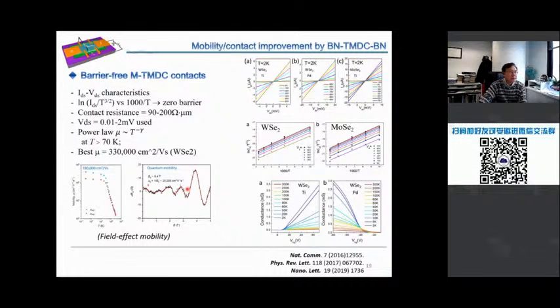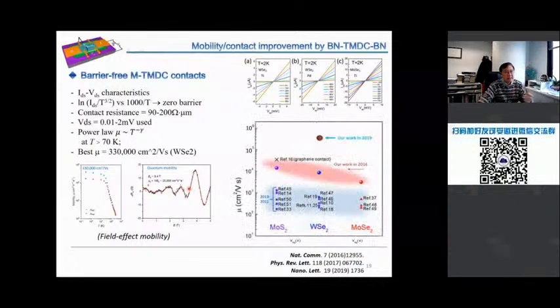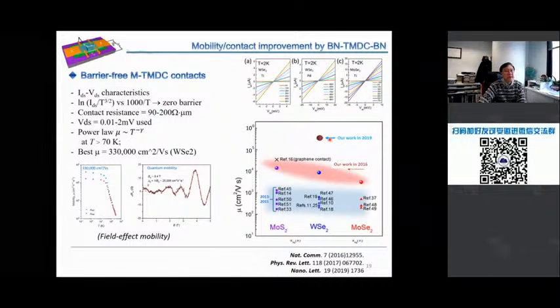So based on this kind of device, we probe very nice quantum phenomena in these materials. I use this chart to show the progress in improving the mobility of these TMDCs. In 2016, the highest mobility we made was comparable to those of TMDC devices based on graphene contacts. And last year, we further improved the mobility to one order of magnitude higher.